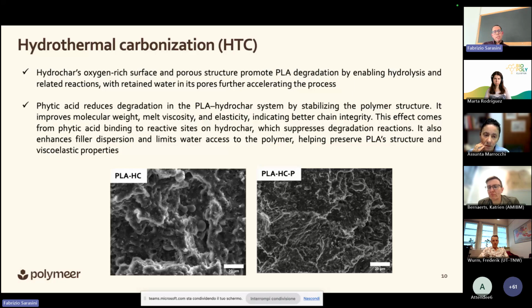acid was also seen as a compatibilizer with PLA, and this can be seen by looking at the fracture surfaces of the samples. Because, for instance, in the unmodified blend, you can see that it is easy to see the particles of the hydrochar, which are very well exposed on the fracture surface. In the second case, as you can see, it's very difficult to detect the hydrochar because it is completely embedded inside the matrix. So meaning that the interfacial adhesion is somewhat increased.